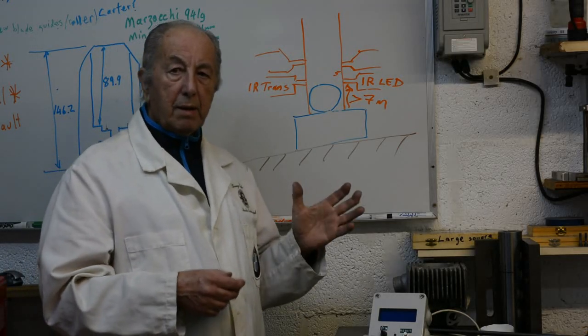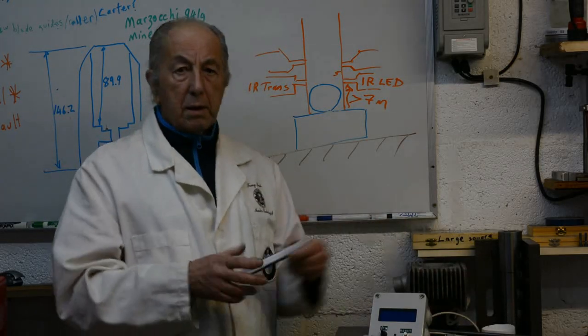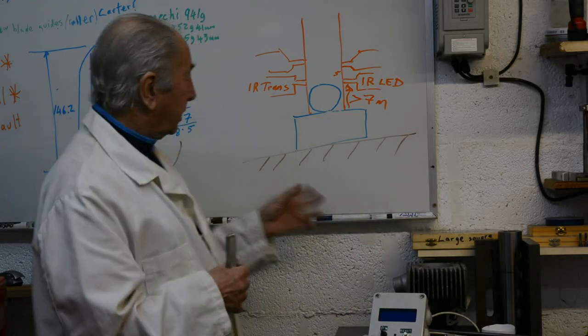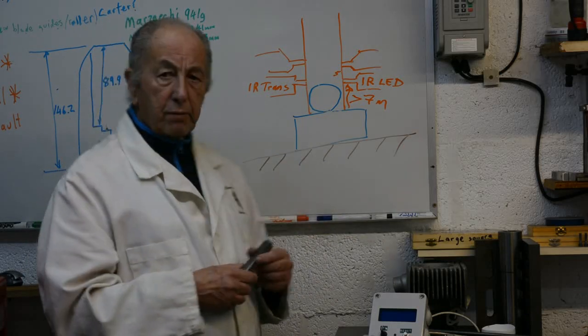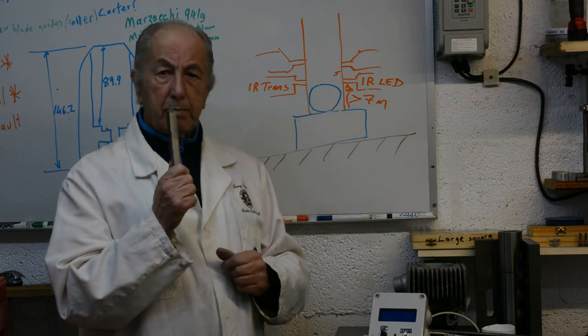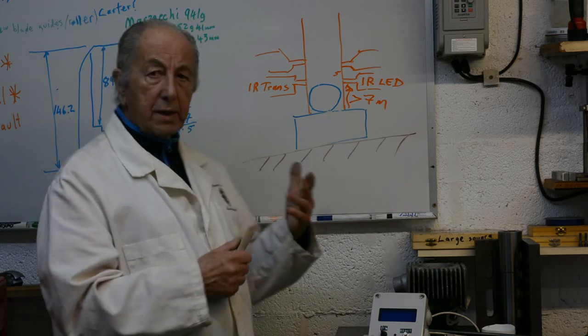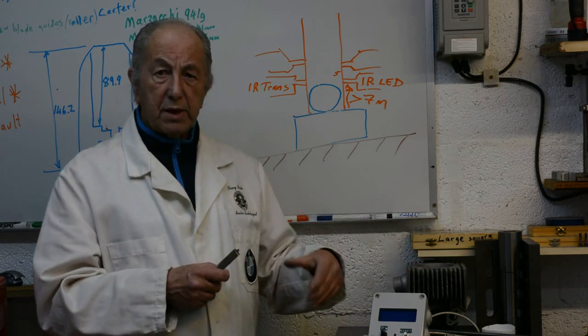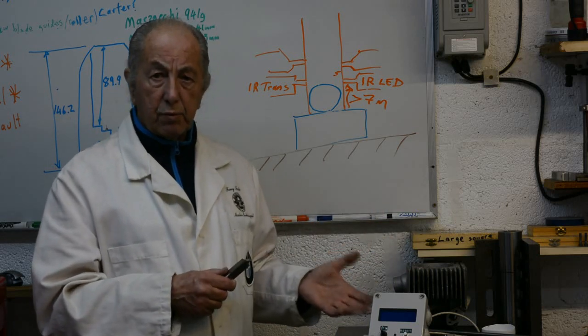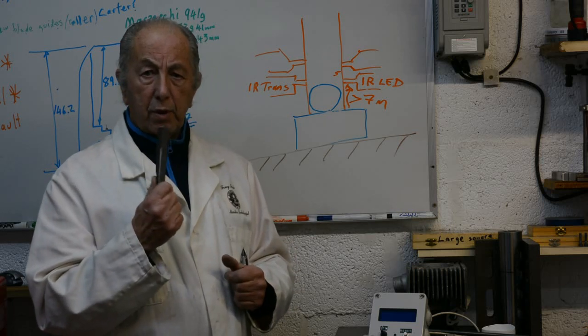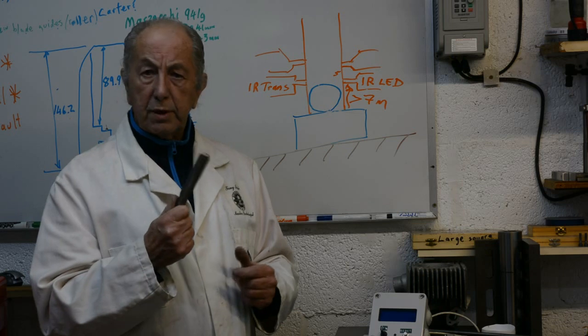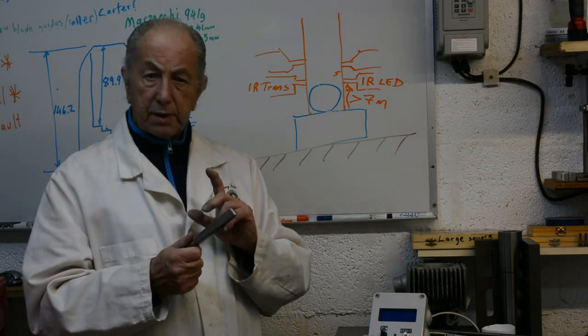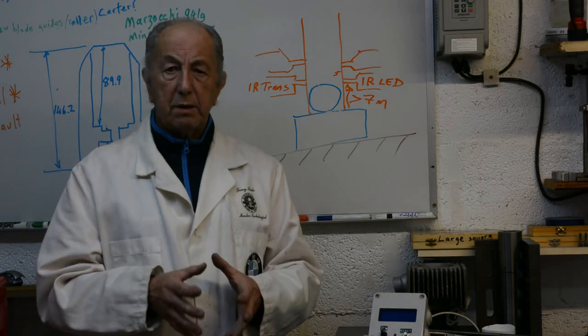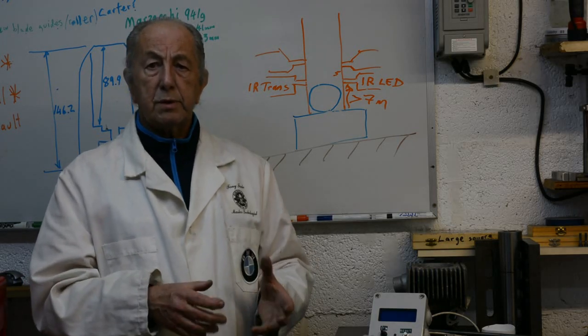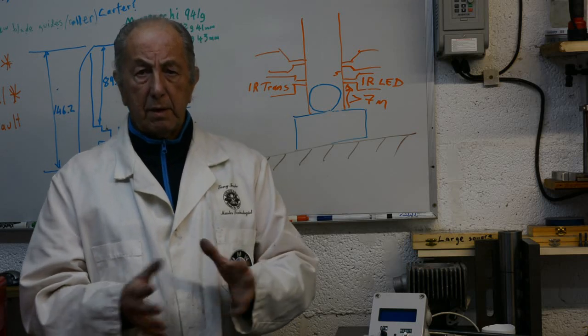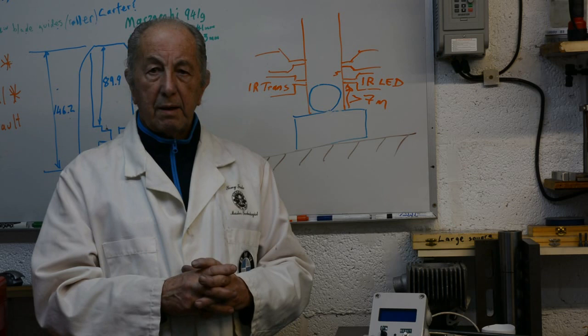Well, I did that. My very first test was without any calibration, purely getting that Leeb number because of the velocity ratio. My first test was on this piece of high-speed tool steel, and after converting the number that I got to Rockwell C according to the Leeb conversion tables, I got a value of 64 Rockwell C for this piece of high-speed tool steel, which is right in the range that you would expect for such material. I then tested other materials and got equally close results to the hardnesses that one would expect for that particular material. I was a happy boy.